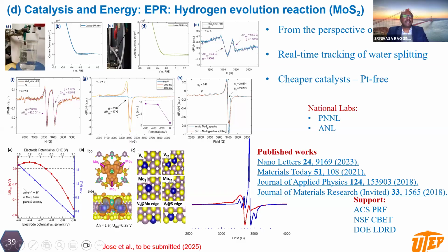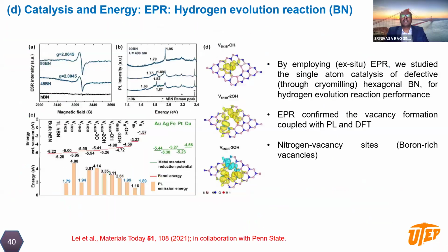And our collaborators did theoretical calculations, and they have shown that the free energy is changing as a function of electrode potential, and as a result of that, you are changing the intensity of the signal or magnetic moment of the signal that is plotted on the right y-axis. So though their curvature is different, their trend is similar. So you see the structures that they considered while computing these free energies. The point to note is that by using a combination of in situ electron spin resonance capabilities plus electrochemistry plus DFT calculation, we can clearly establish what exactly is happening during a hydrogen evolution reaction. So going further,